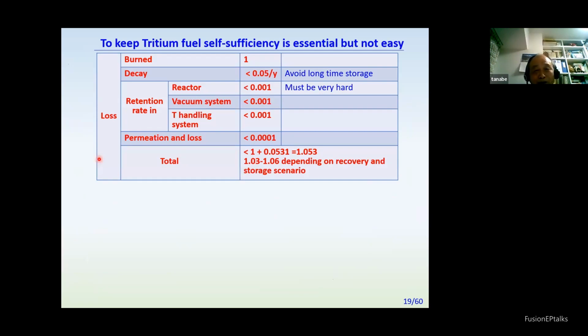A simple expansion can be made: if only 1 is burned, then there's loss. This is the burn loss, and this decay rate is 5%, but this depends on how it's stored. In any case, retention in the wall or vessel, I assume this is 0.1%. So the total loss comes to something like 1.05.